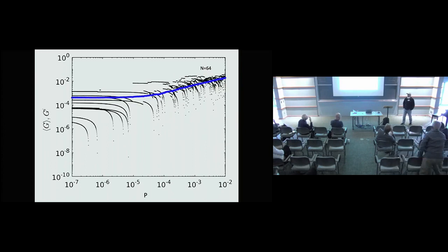Very quick one. To make your life easier, let's go to the infinite friction limit, right? And you are isostatic. So that is well defined, right? I mean, infinite friction, isostatic. But the coordination number is going to be different. In that case, I think you will get an anisotropic shear modulus. Yeah, I think I agree with that. I don't think people have proved that yet, but that's the direction I'm going. I think you can get anisotropic elasticity even with frictionless.